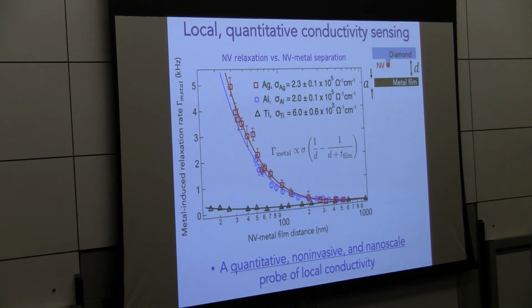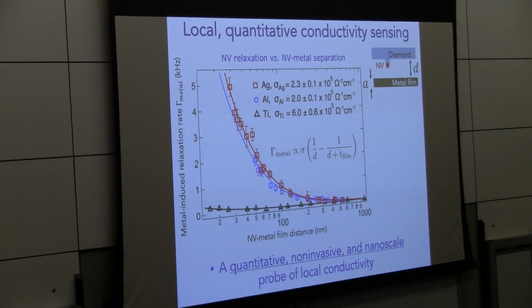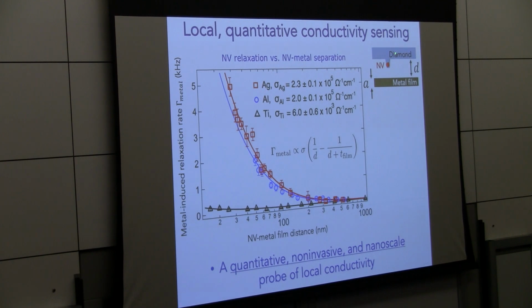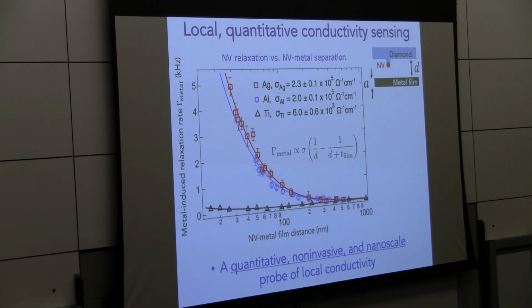This is also quantitative. I already showed you this equation that relates the noise power spectral density to the conductivity. And just to show you this quantitative nature of this imaging, as a function of height, we measured the T1 of an NV as a function of distance to some metal film, for 3 different metal films. As we bring the NV closer to the metal film, the relaxation rate increases. Fitting this curve to this functional form, which I already showed you, which is proportional to the conductivity, we can fit for the conductivity of the metal films, and indeed find different values for silver, aluminum, and titanium. These values are to be expected. They're somewhat consistent with what one would expect, a little bit lower than bulk conductivity, which is also expected given that these are thin films.